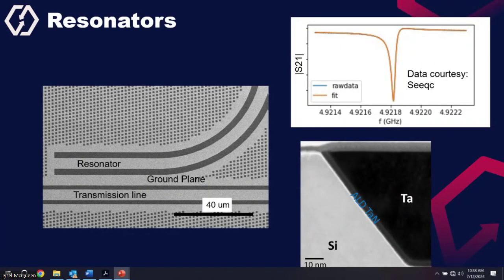So tantalum, silicon, tantalum. And we need these patterns, which are known as dummy fill, which are basically silicon holes. So these are the cheesing. Like in butter, we make holes, like cheesing. So these are required to have a uniform pattern density across the wafer, so that after the CMP, we get the same result everywhere. It's not like some portion is over polished and some portion is less polished. So that's the purpose of this. And the second purpose is, in qubit devices, you will usually see this, so that there is no flux trapping and other effects. So it serves two purposes for us.